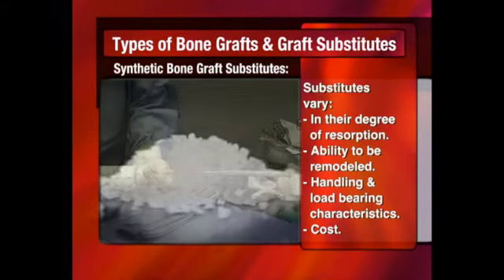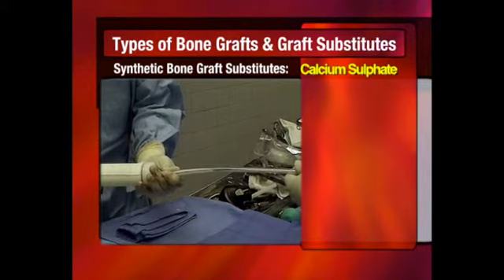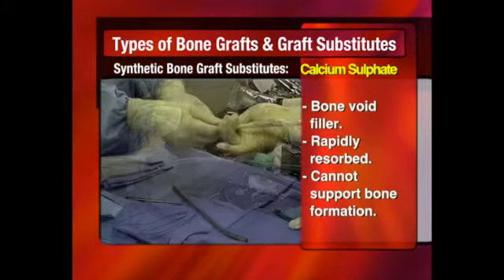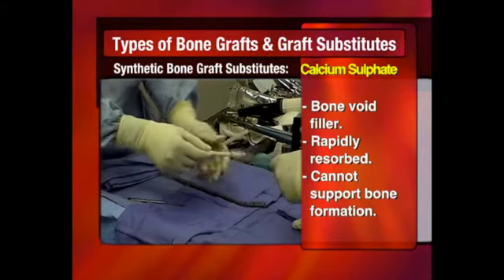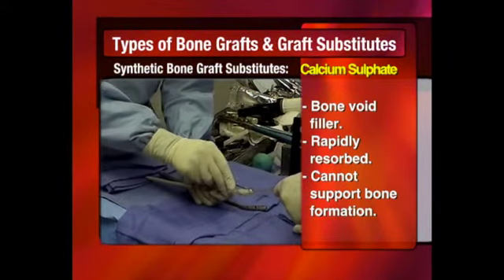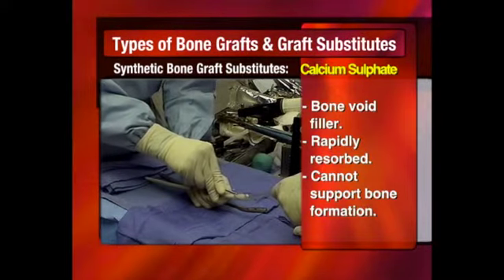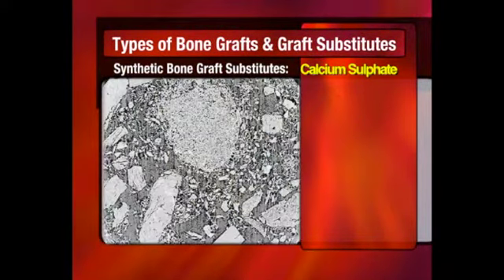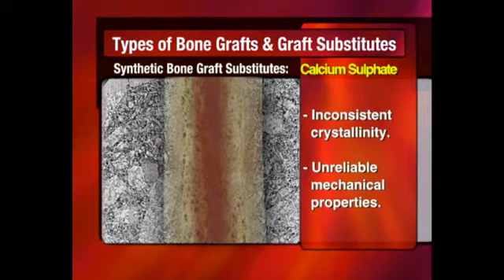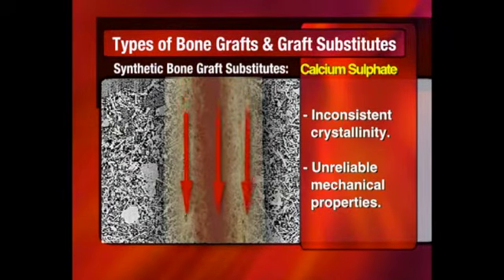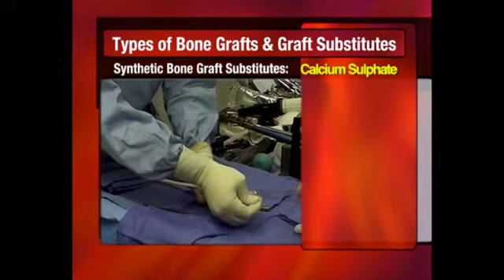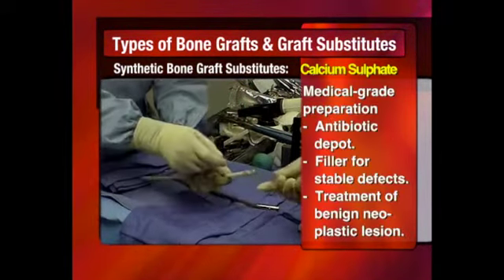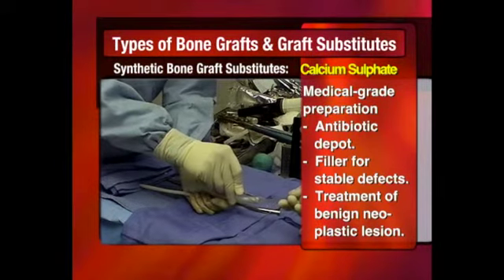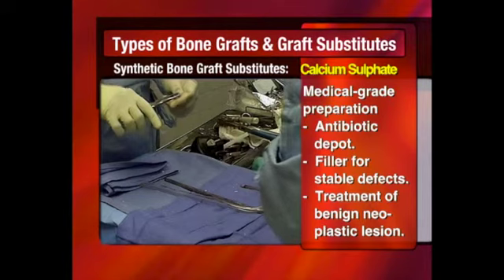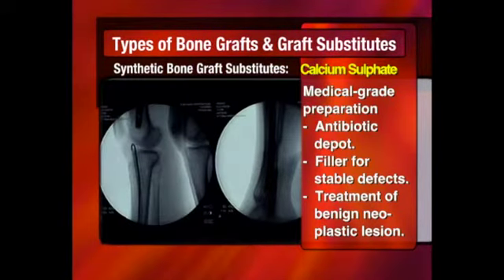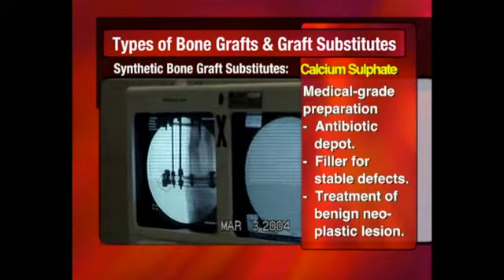Furthermore, the various bone graft substitutes vary significantly in their degree of resorption, ability to be remodeled, handling and load-bearing characteristics, and cost. Calcium sulfate, or plaster of Paris, has been used as a bone void filler since the 1950s. It is rapidly resorbed and replaced by bone. In fact, it resorbs too quickly to provide a support for bone formation. Calcium sulfate preparations have been inconsistent in their crystallinity and therefore have unreliable mechanical properties.